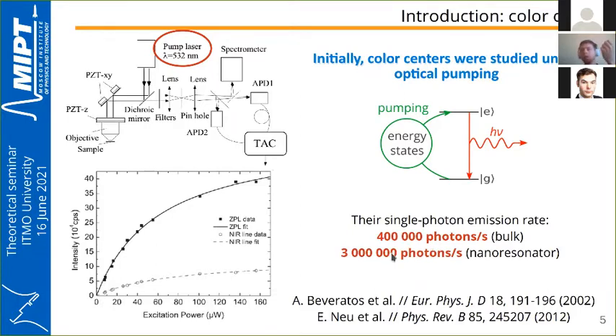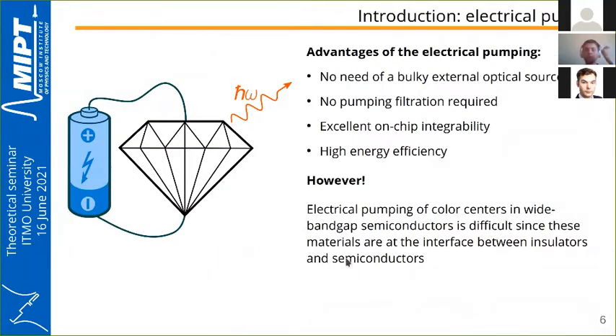For comparison, quantum dots at room temperature emit less than 8,000 photons per second. However, from a practical point of view, optical pumping is not promising. Instead, it's better to use electrical pumping, where we take our diamond diode and pass current through it, because there is no need for a bulky external optical source, no need for pump filtration. Moreover, we can take millions of single photon sources and put them on a chip, and by passing current, efficiently excite them to emit photons.